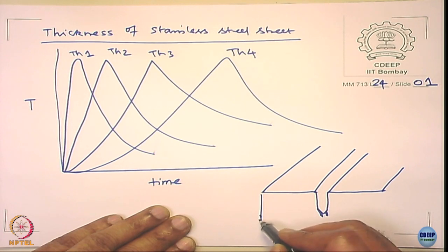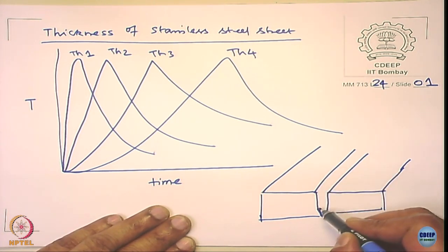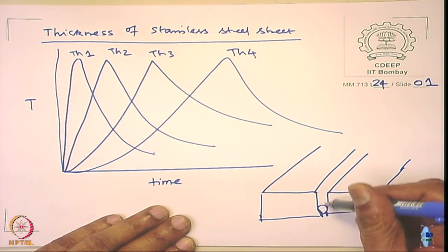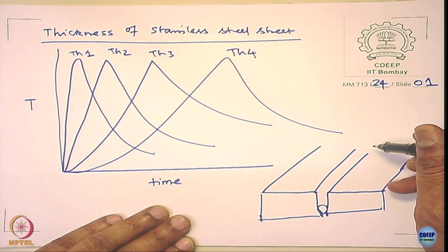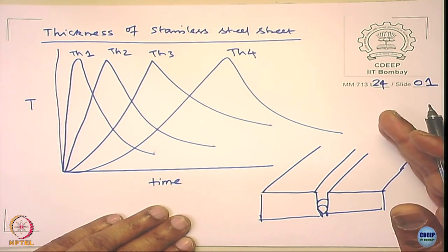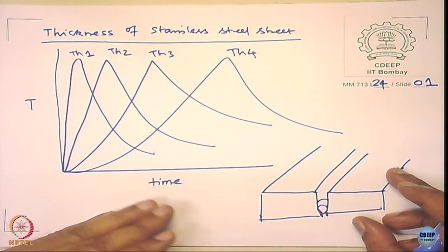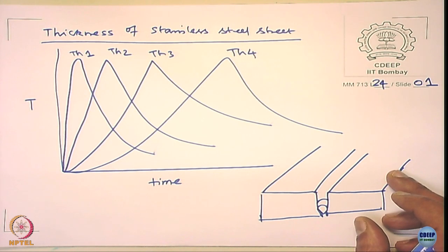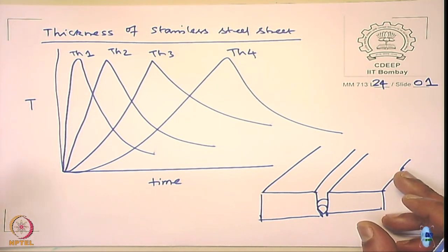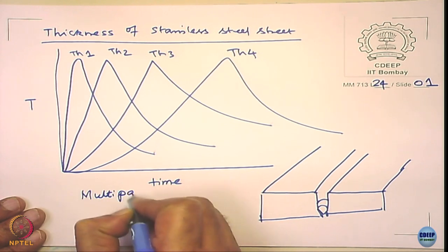Yes, it is a good answer. So, you do not deposit at one go. You deposit once, continue the layer, allow it to cool, then you deposit the second layer, and allow it to cool. So each time you weld, you are allowing the weldment to lower its temperature. In this process you are able to maintain an adequate cooling rate so that sensitization is avoided. So, we do what is called multipass welding.